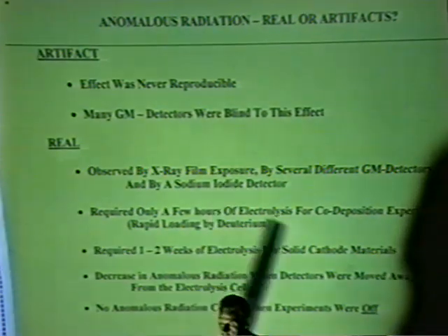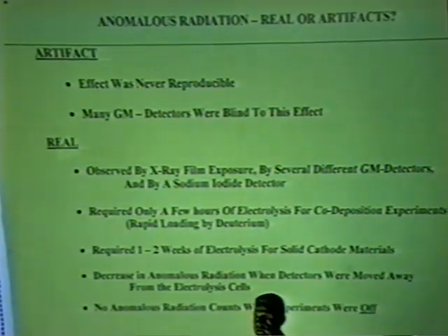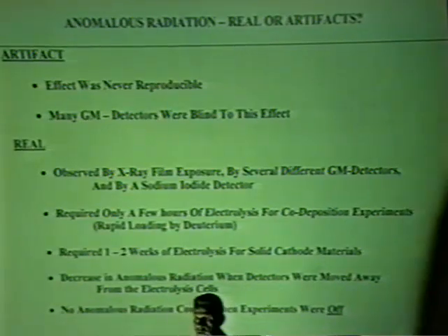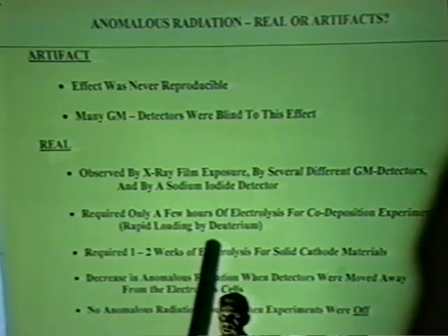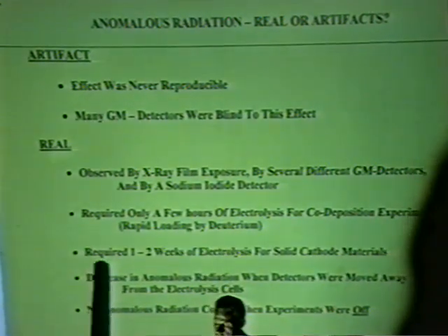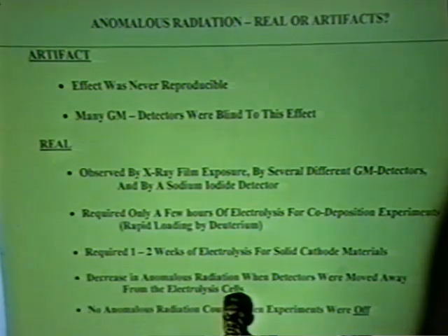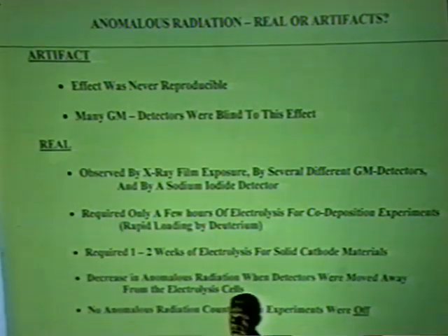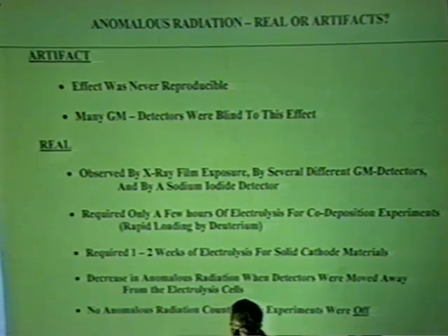The reasons why we think it's real: it's observed by other methods, X-ray film exposure. Several different detectors showed similar effects. Also, sodium iodide detectors showed an effect. In the co-deposition experiments, the effect showed up within a few hours. With solid rods, it took 1 or 2 weeks. How could this just be a coincidence? That's my question, because we know it takes a rod longer to load.